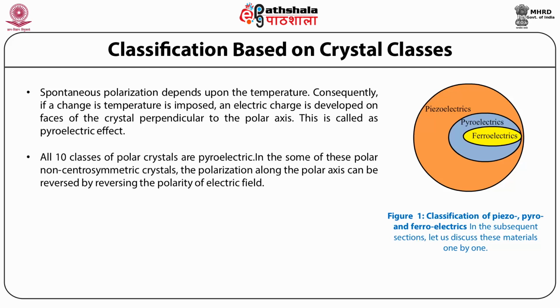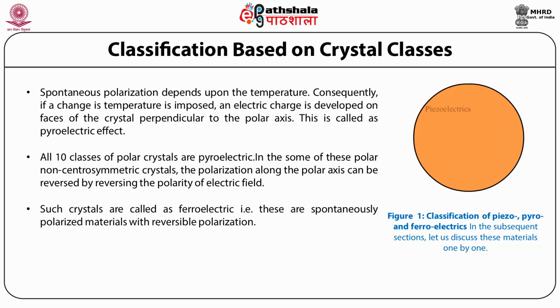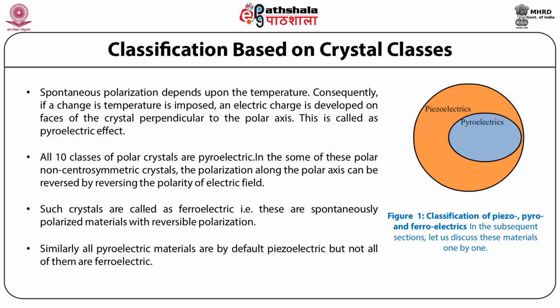All 10 classes of polar crystals which we have discussed previously are pyroelectrics, and in some of these polar non-centrosymmetric crystals, the polarization along the polar axis can be reversed by reversing the polarity of the electric field. Such crystals are called ferroelectrics, that is, spontaneously polarized materials with reversible polarization. By default, all ferroelectric materials are simultaneously pyroelectric and piezoelectric. Similarly, all pyroelectric materials are by default piezoelectric, but not all of them are ferroelectric, which can be seen in this schematic.